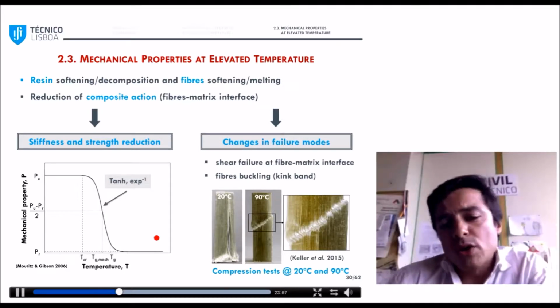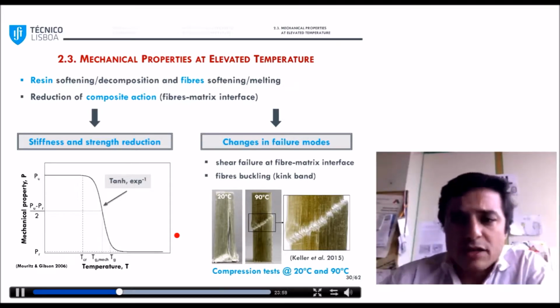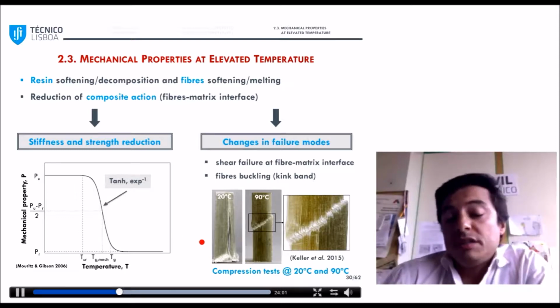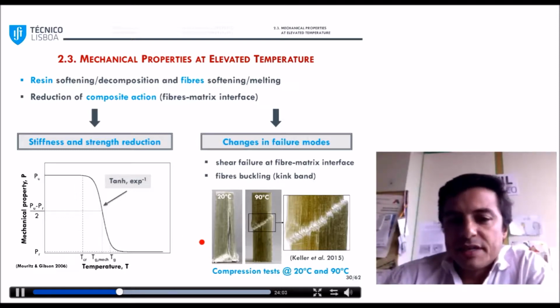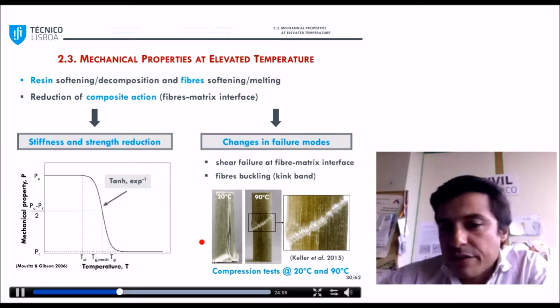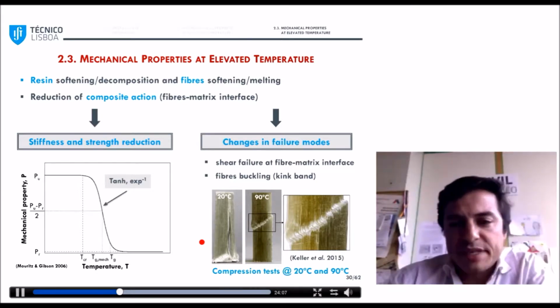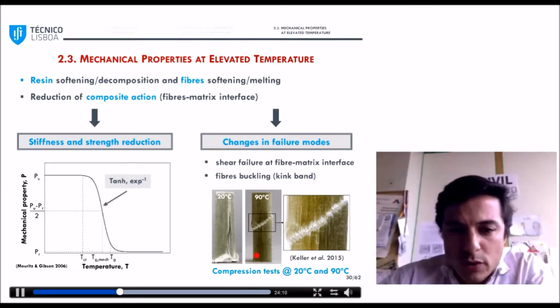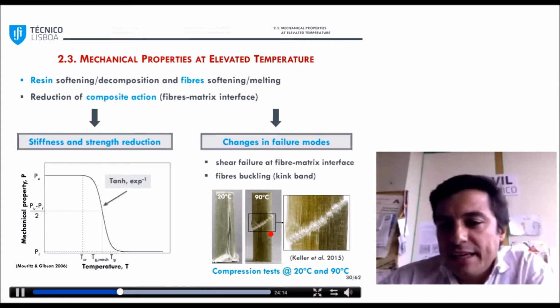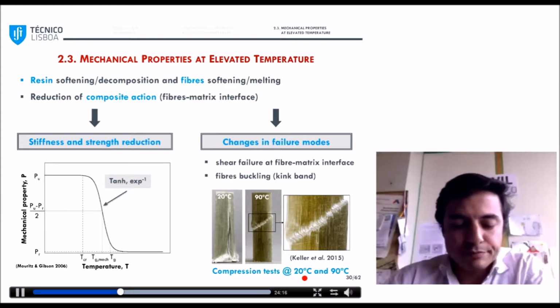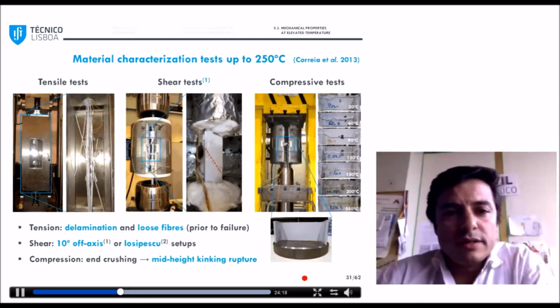And at the same time, we'll also have changes in the failure modes. So it is more likely that at elevated temperature, we have shear failure at the fibers-matrix interface, and also, as you can see here in these two figures, fibers buckling or kinking under compression.